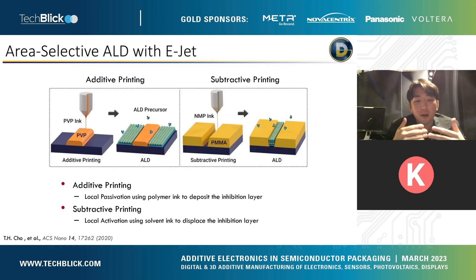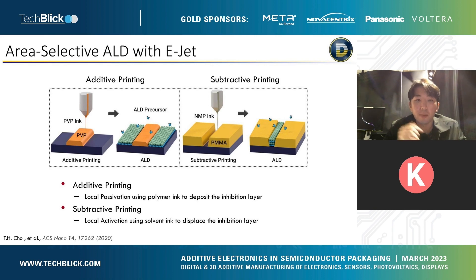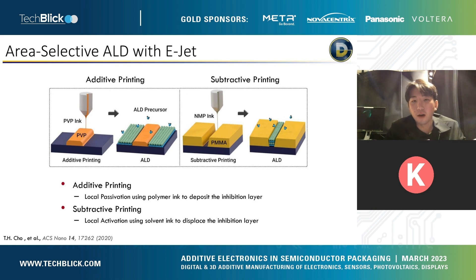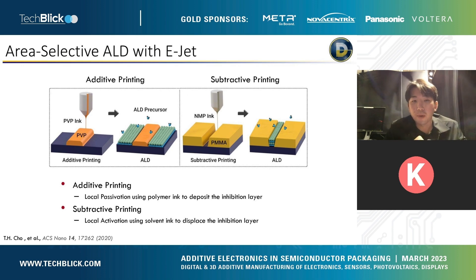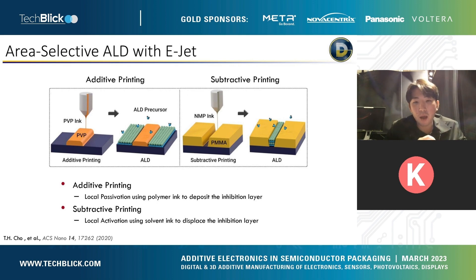These are the two processes we propose to achieve by combining E-jet with area-selective ALD. The first is additive printing, where we print polyvinylpyrrolidone (PVP), which acts as an ALD inhibitor to passivate the surface towards ALD growth. The second is subtractive printing, where we pre-pattern the surface with PMMA (polymethyl methacrylate) and use NMP (N-methyl pyrrolidinone) ink, which is a solvent for PMMA.